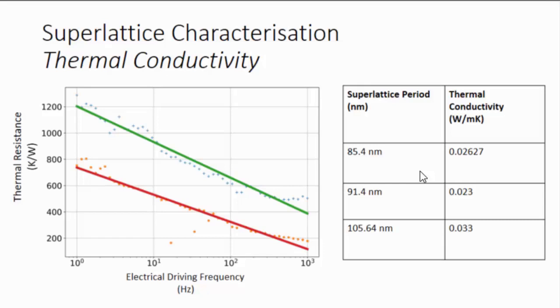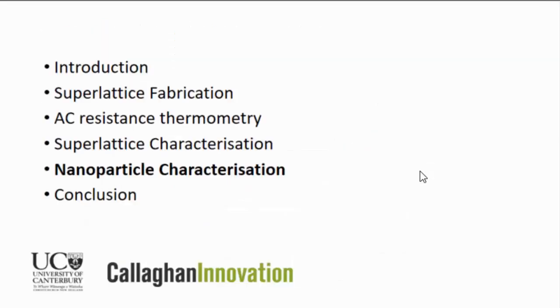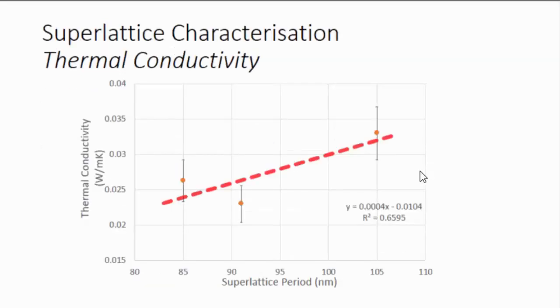The original creators of this particular phononic crystal reported an increase in the bandgap of the phononic material with a decreasing period, which is what you would expect. However, when we tried to correlate this with thermal conductivity, we got a moderate R-squared value at best, which essentially implies that there is another mechanism at work here at room temperature when measuring the integral of all the thermal energy carriers via the thermal conductivity.